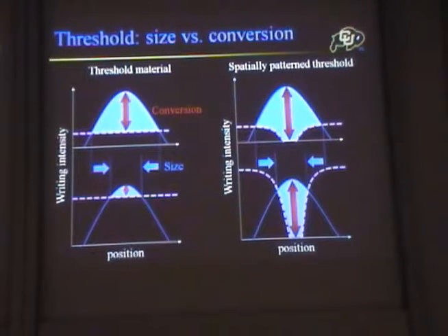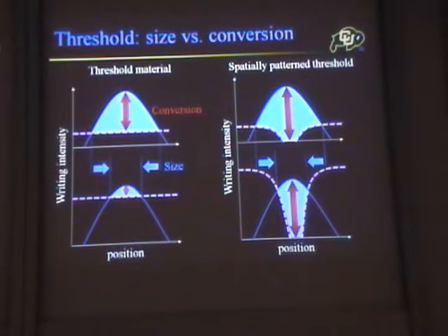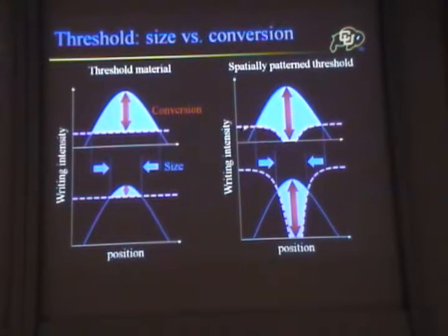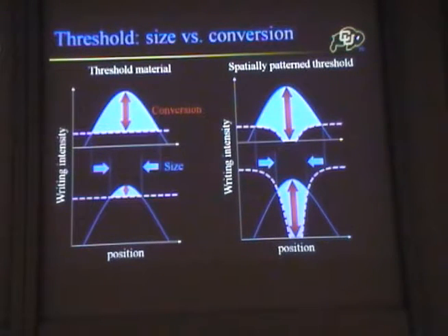This is a game you do play in two-photon stereolithography—you dial your intensity down so the polymer you make can just survive. But it's clearly a diminishing return. If I push this threshold higher and higher, I make smaller and smaller features, but eventually the feature is not stiff or robust. What if I could change the shape of this spatial profile of thresholding—threshold a lot at the wings and not in the middle? Now as I push the threshold up, I make a smaller feature without any penalty on how strong a feature or how much chemistry I get to do at the focus. That would be a cool thing.